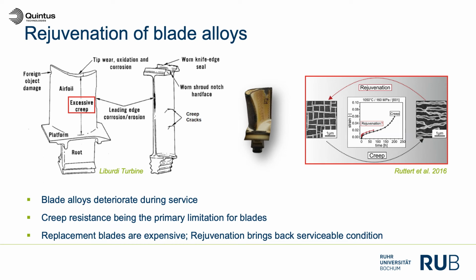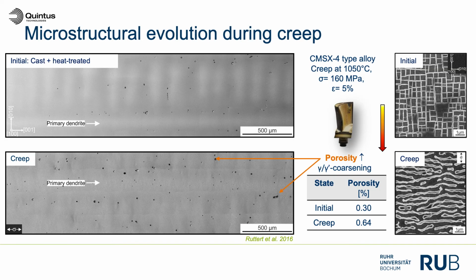We have the very expensive single crystalline materials. A lot of expensive raw materials such as rhenium or tungsten are alloyed, and also the blade itself costs a lot of money. And when we look onto a turbine blade after service, it can show an internal and an external degradation. And the rejuvenation focuses on the internal degradation, because after a certain time in service we have a